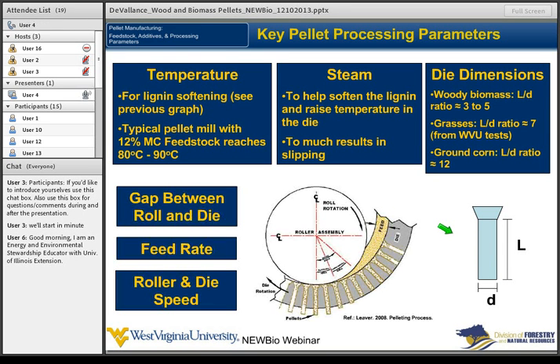So this is what happens in the die. So you have this roller, your feed comes in, and as this roller rotates this way, your die is going this way in terms of the ring type. You start forcing that material down through these channels. So a lot of things play a role in that, like the gap between. So how much gap do you have in here between the die and your roller? How fast are you feeding that material in, and how fast your die is going around.